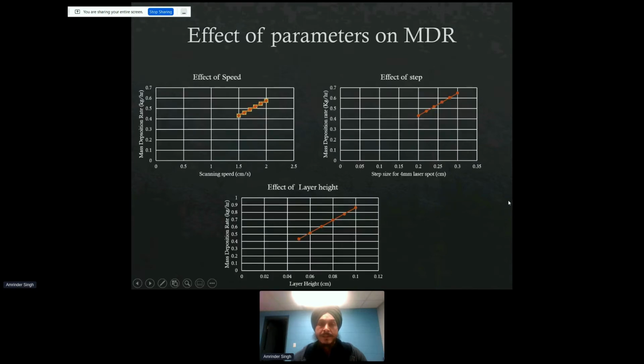So as we can see, all those parameters affect our deposition rates. Mostly the layer height is the key parameter which affects our deposition. So the higher the layer height is, you can see we have gone from 0.05 to 0.1 centimeters. We have gone pretty much to 1 kg per hour. So it's a significant improvement.